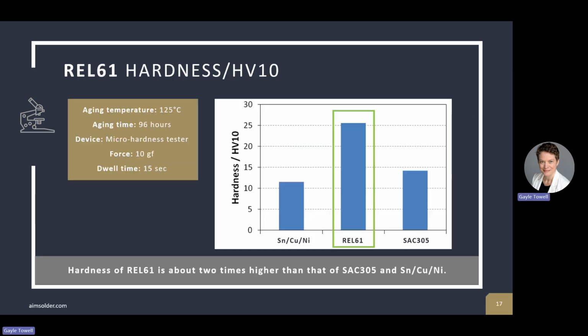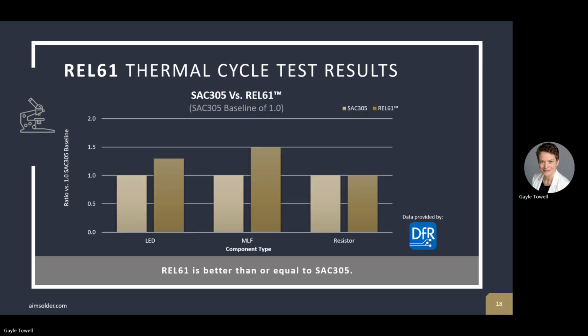If we compare hardness, REL61 has a hardness that's about twice that of SAC305 and a tin copper nickel alloy. We've also looked at thermal cycle test results with this alloy. So here we are comparing REL61 with SAC305, treating SAC305's performance as the baseline and looking at the results across different components. We see with the 3 different components tested that REL61 performs either equal to or better than SAC305.